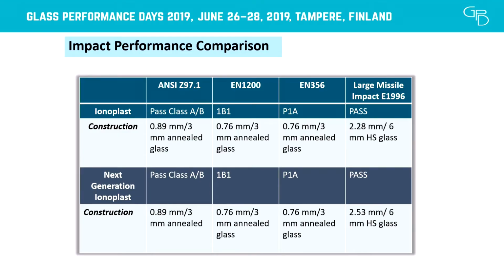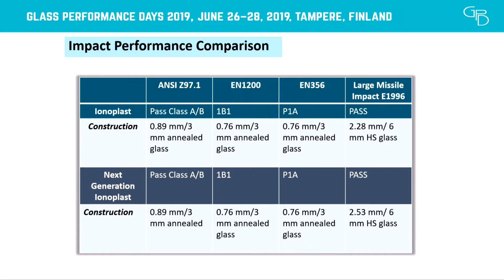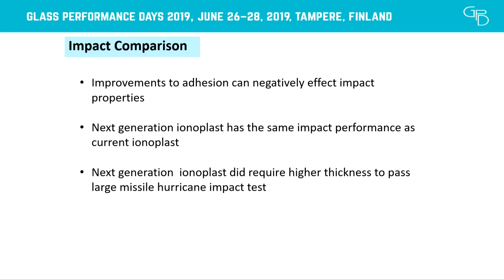Impact performance. One of the concerns we had is maintaining its impact properties, and when you increase adhesion, you can negatively affect these. So we wanted to see if we could pass the same constructions we do with the current Ionoplast, and we do. You can see for 0.89, we passed the ANSI Z97, EN 12600, and EN 356. The only thing that was an issue is the hurricane impact testing. We did have to go up a little bit in caliper to pass the large missile impact. So again, in the impact comparison, improving adhesion can negatively affect the impact performance. The next generation Ionoplast has the same impact performance in most cases, except for the large missile impact for hurricane.